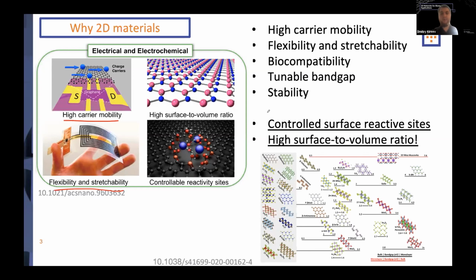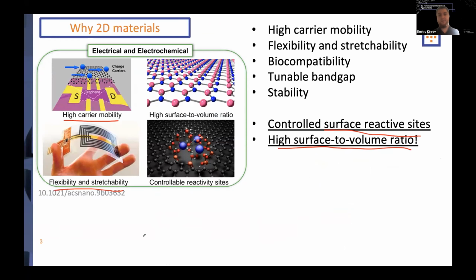The last 2 really important parameters on why 2D materials make excellent biosensors are the controlled surface reactive sites and high surface to volume ratio. Why is it important? Let's say you have an electrically conductive graphene or MoS2, and you put it in a liquid to make a biosensor. These devices would be sensitive to literally anything with a charge. You get a charged molecule, you receive a reaction. This is not a biosensor per se, because it's not specific to a molecule. To make specificity, you need to functionalize the 2D materials with recognition elements, as I introduced earlier, the receptors.